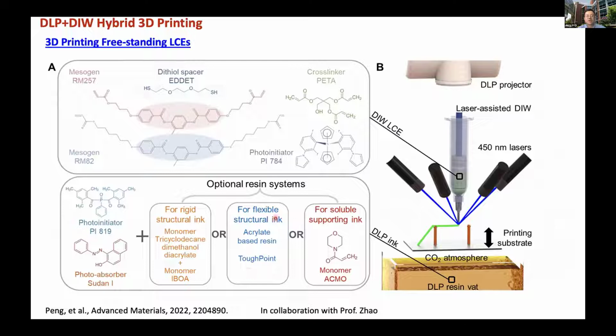So we're using our DLP and DIW approach. Here's basically the setup. We have a DLP resin. We try to print some either support structure or sacrificial structures. And then we try to write the LCE line in the air. In this case, we need to overcome several challenges. First of all, because I have both the DLP ink as well as the liquid crystal elastomer ink, and I have lasers that are on all the time during the printing,